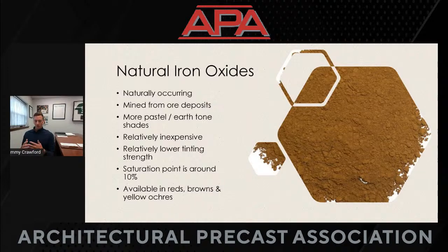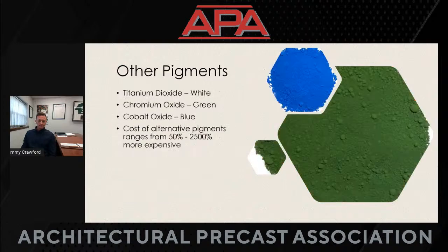But if you're looking for more of a pastel or earth tone shade, natural iron oxides are going to have more success on a consistent basis producing those colors. Saturation point is around 10%. So adding more than 10% is not going to achieve any more color change. We typically recommend not going over 5%. And we'll get into why. There's some strength-related stuff that we'll get into on the ASTM testing stuff. As I mentioned, they're available in pastel and earth tone shades, typically reds, browns, and yellows.